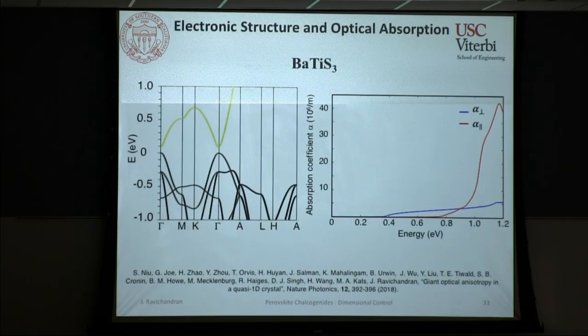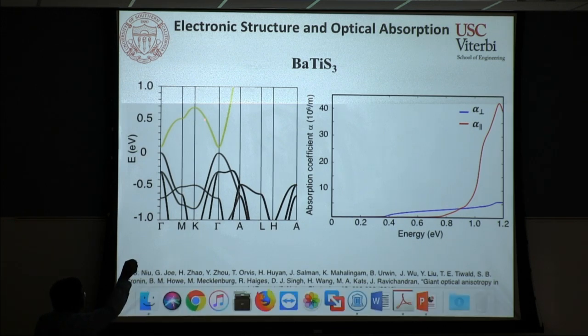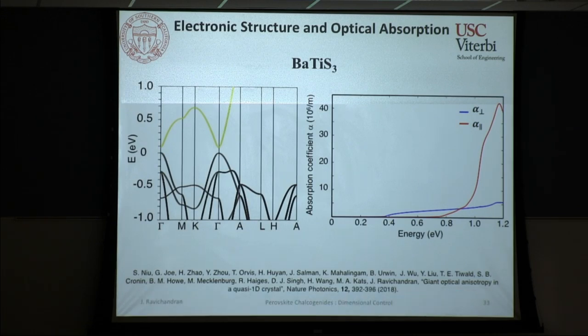So we did the DFT calculations, and we were able to find the dispersion, the band structure for this material, and the band structure itself looked very symmetric. So we thought that this material, despite being structurally very anisotropic, may not be optically very anisotropic. But surprisingly, once we calculated the absorption coefficient, what we found was that along the 1D chains and across the 1D chains, the absorption coefficients are very, very different. This is primarily because the coupling coefficients along the two different directions are very different, so the seemingly symmetric band structure does not tell the whole story.